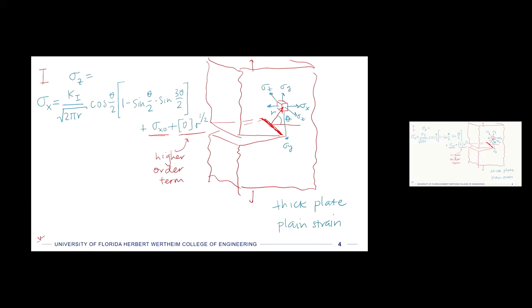So now let's look in the y direction. We'll have something similar. So we still have that K1 divided by square root 2 pi r, because we're in the same mode, we're the same location. And then some of these geometry terms are similar, but not exactly the same. So we still have a coefficient of cosine of theta over 2. And then instead of a 1 minus sign, we have a 1 plus sign in the middle here. We still have the same product, sine 3 theta divided by 2. Then we'll add on a higher order term of r to the 1/2.